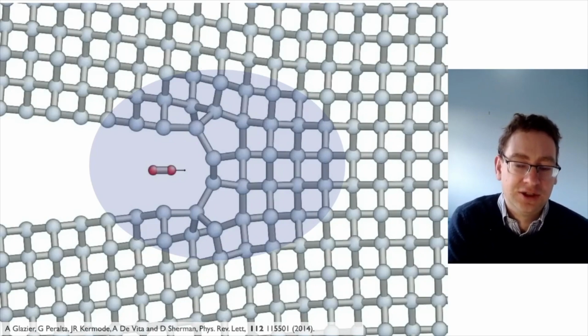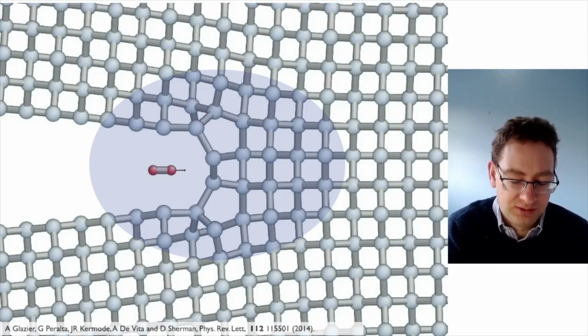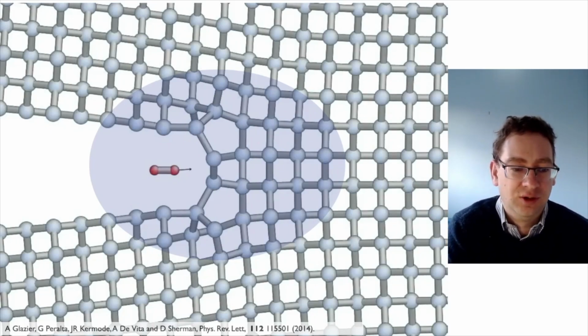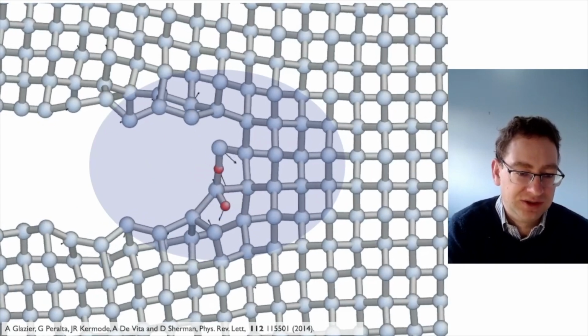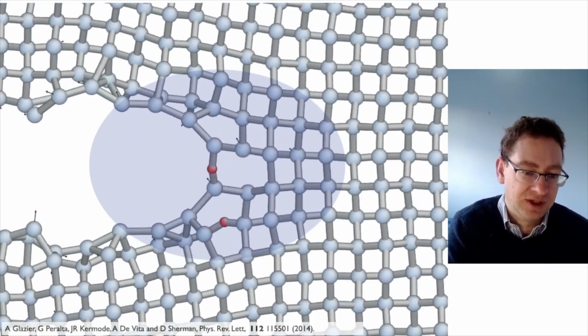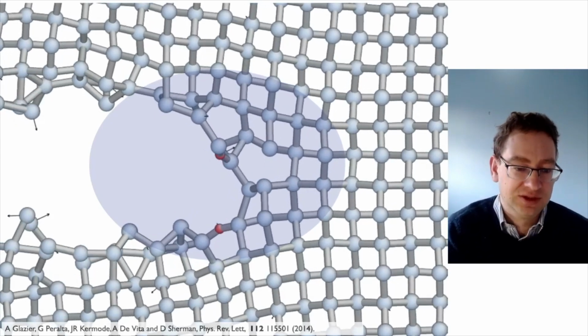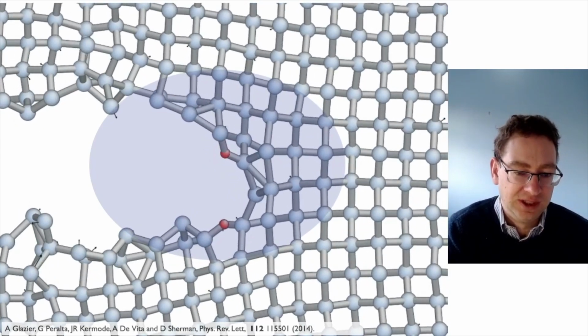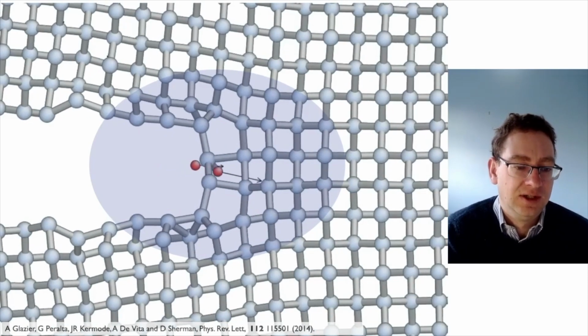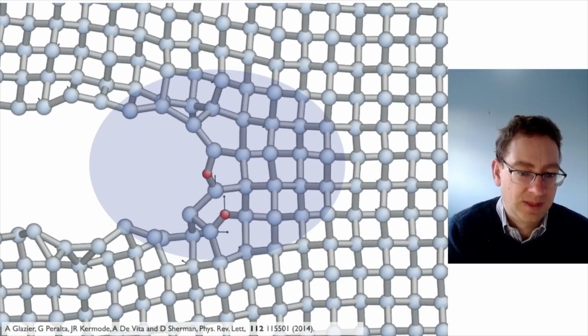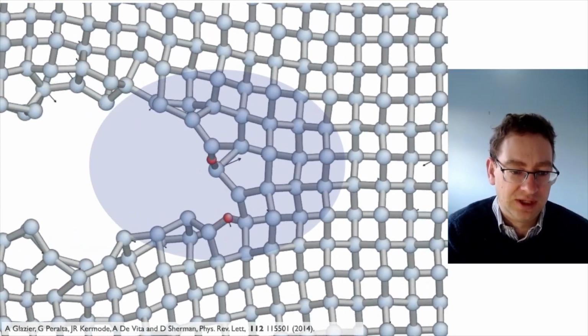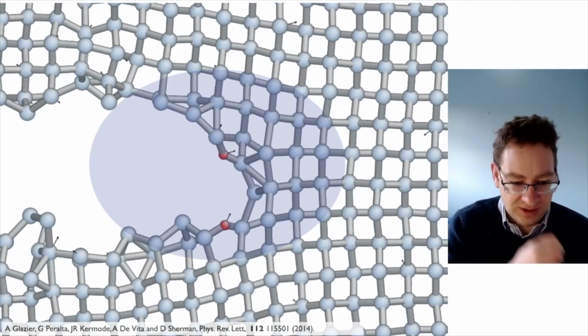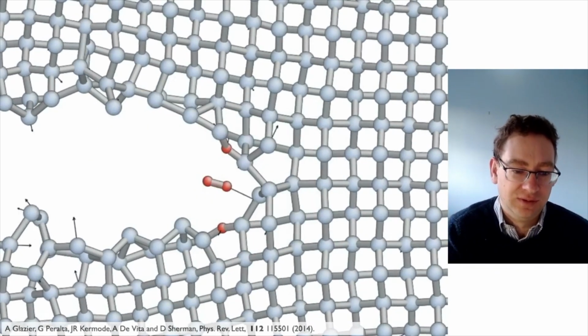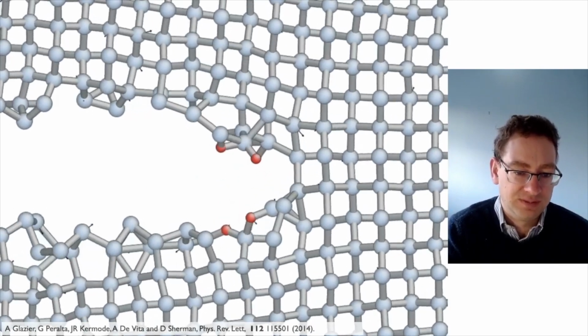The last example I want to show you is what happens if you put water or oxygen, if you put molecules into the situation. They can actually react and perform chemical reactions which can break bonds when otherwise you wouldn't be pulling hard enough to do so. This is called stress corrosion, and it's what happens perhaps in the glassy door that I showed you at the beginning. So in this case we've got a molecule of oxygen that's coming in, let's just see that again, and causing bonds to break when otherwise we wouldn't be pulling hard enough for them to do so. This makes cracks propagate very, very slowly because we have to wait for another molecule to get there before the next bond breaks.